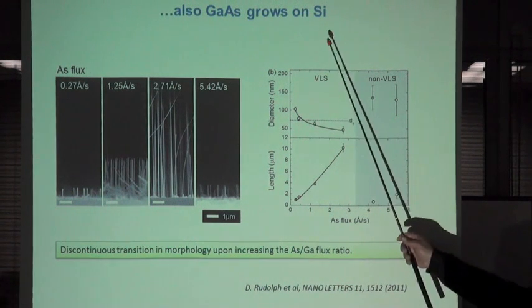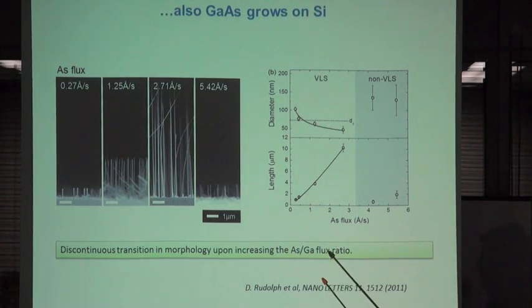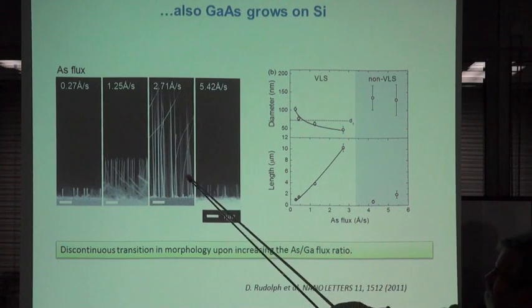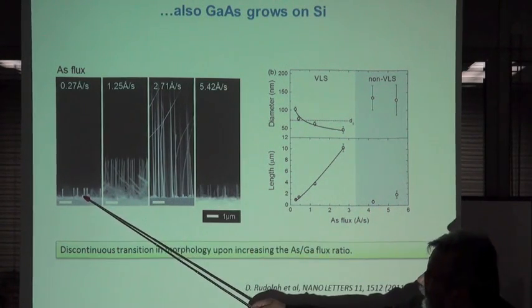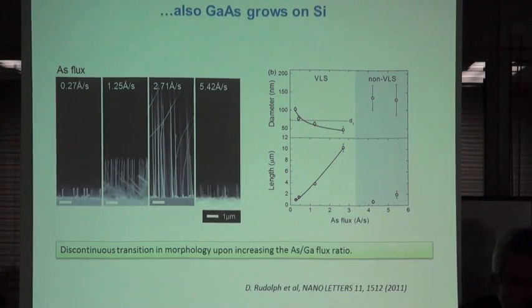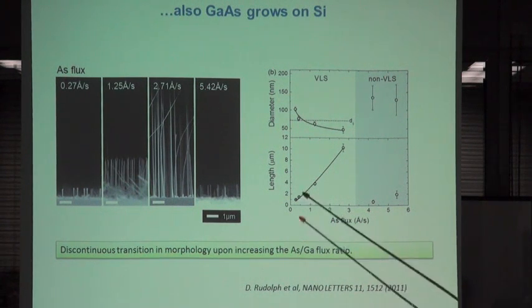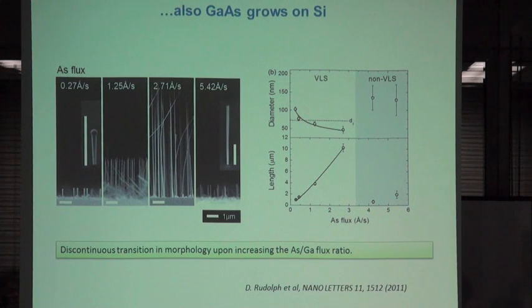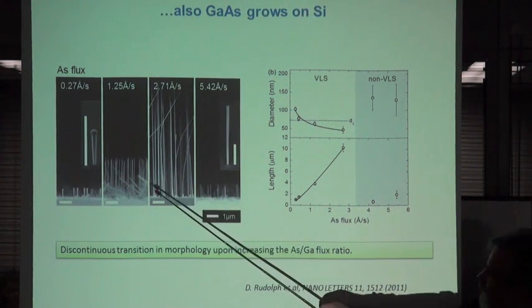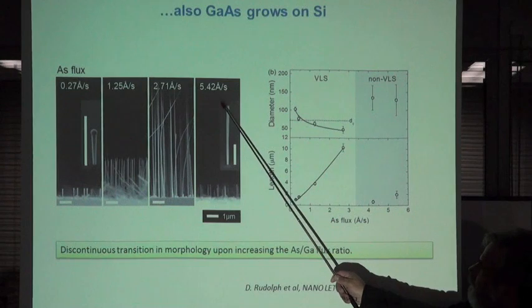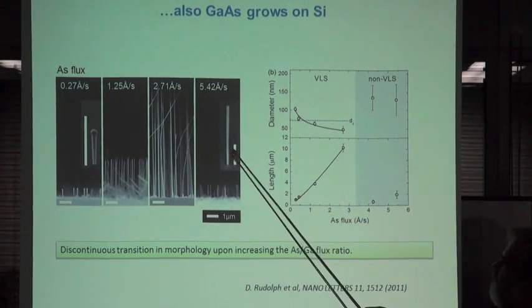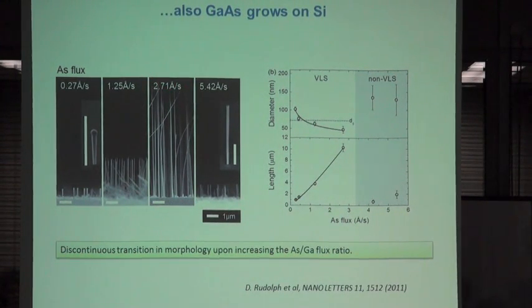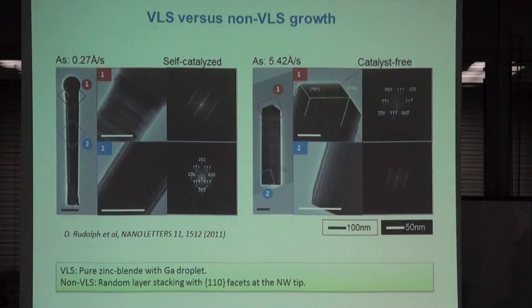We can do this also for gallium arsenide on silicon. The yield is not so high. So this is just a parameter like the arsenic flux. These are gallium arsenide wires on silicon. In this case on unpatterned, just random holes. But we can also switch here from the vapor liquid solid growth with the droplet to non-vapor liquid solid if we increase the arsenic flux. If the arsenic flux is high enough, then we get, let's say, not this gallium droplet, and we start immediately with the growth of these wires.